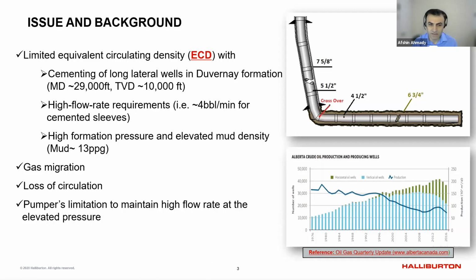At the same time, they had high formation pressure, so heavy mud in the hole. You need to follow the rheological hierarchy and density hierarchy, and cement density cannot be less than some value, so you have a restriction there. And with a high pumping rate, the downhole pressure as a result will be high if you don't do anything. Gas migration was another challenge there. So cement cannot simply be designed with low rheology while sacrificing the gas control property of the cement. Loss of circulation was an additional challenge there.